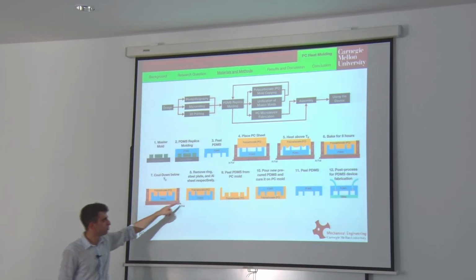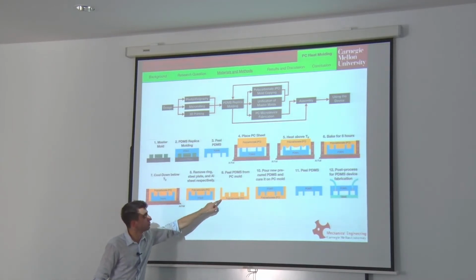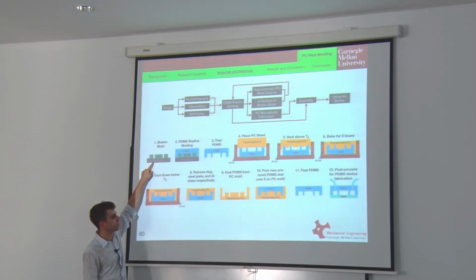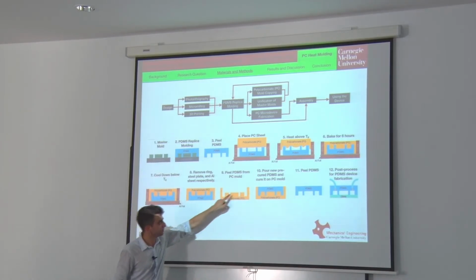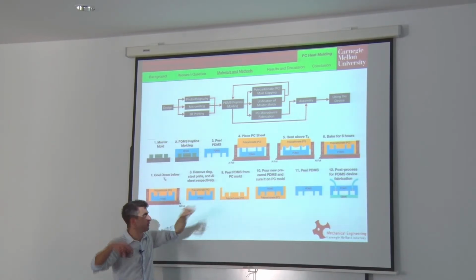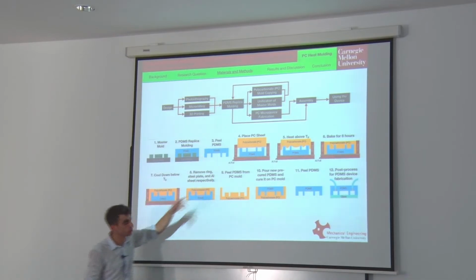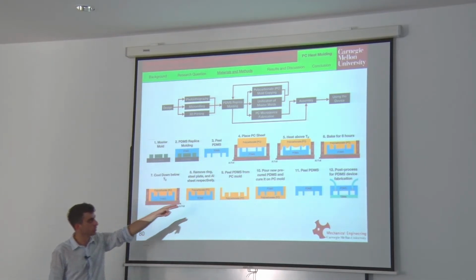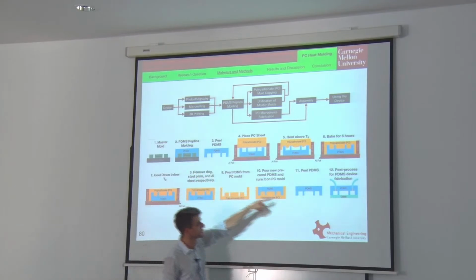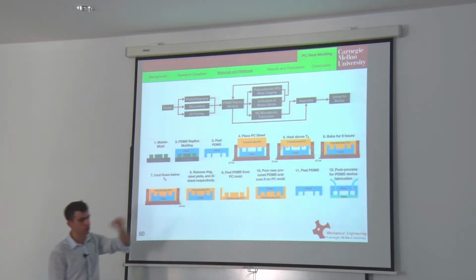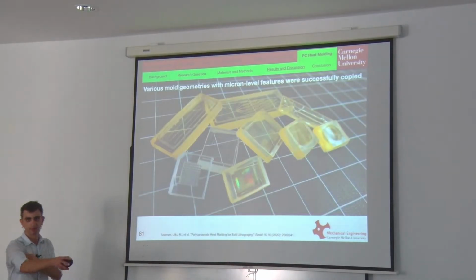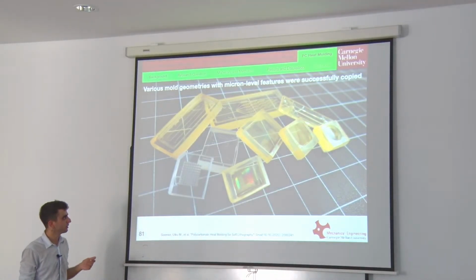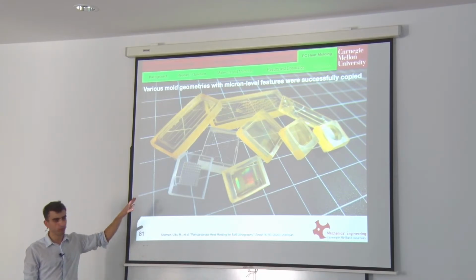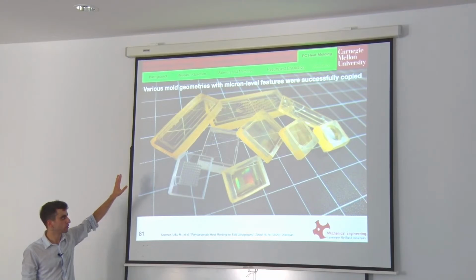And if you remove the PDMS, you create a mold that is exactly the same as a silicon wafer. These are just the side walls that define the height of the PDMS, which is also useful. And you can use this polycarbonate mold to make the same devices, the same PDMS. So I made tens of microfluidic channels using these copy molds, and I created copy molds for all sorts of different microtopologies.